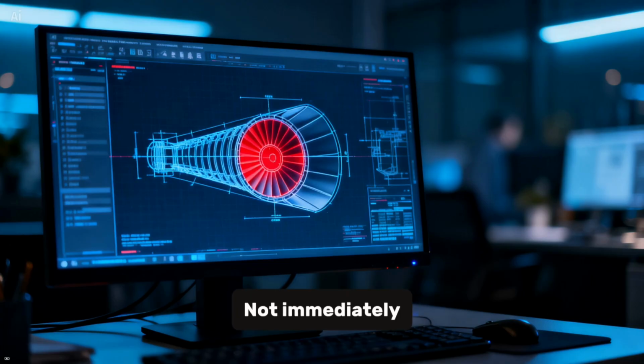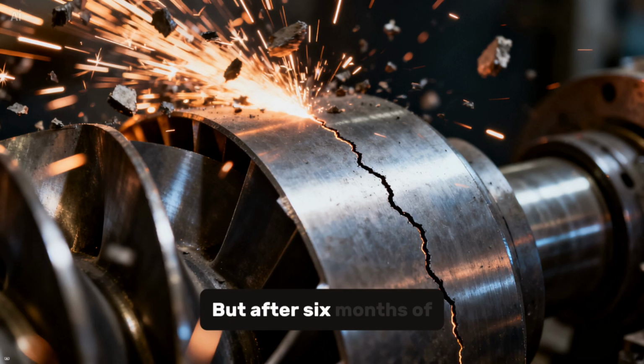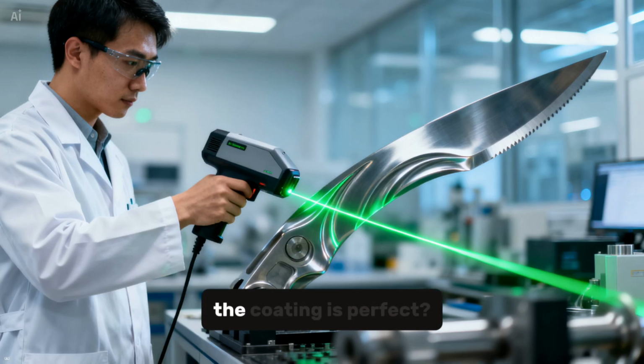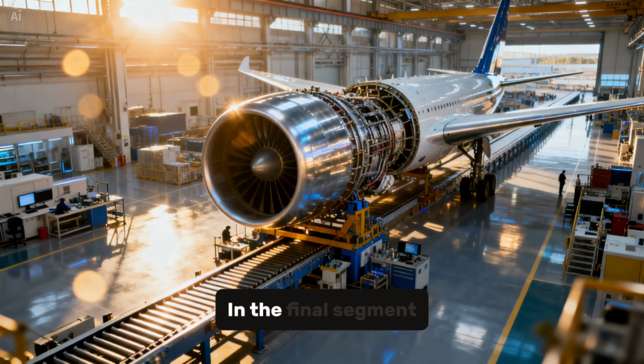Not immediately. Not obviously. But after 6 months of service, the blade develops a crack. The crack spreads. And then, without warning, the blade explodes. So how do they know the coating is perfect? How do they inspect something 3 microns thick on a blade with curves and angles? In the final segment, we'll see the inspection process that catches defects smaller than a bacteria and reveal the staggering truth about what it takes to build one engine.